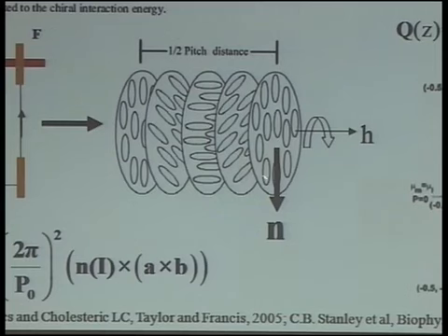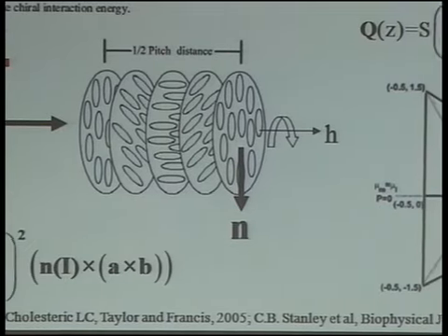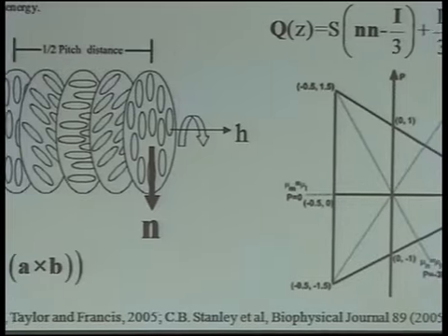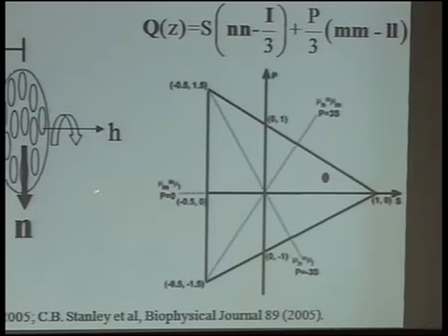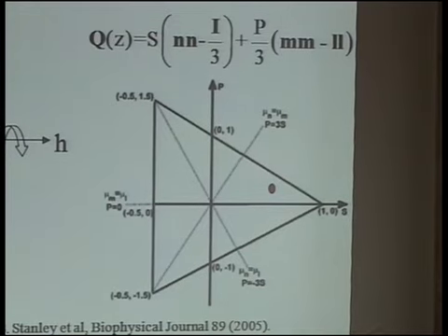The other point, as I mentioned, if you take the plane perpendicular to the optic axis n, that plane is not isotropic. Therefore, in this phase plane that we introduced a few weeks ago, that describes all the possible ordering states S and P, the vertical is P, the horizontal is S. So all the possible states of this chiral nematic live inside this triangle, and you can see that the plane perpendicular to n is not isotropic, so you have biaxiality.